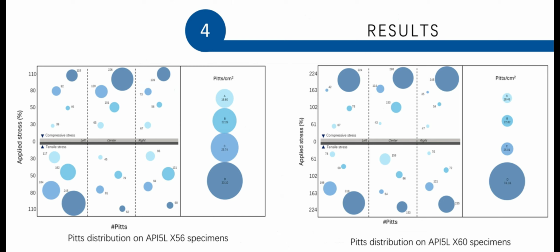Now, what were the results we obtained? Since pits are nucleation sites for cracks, a count was performed on each specimen. It was observed that in both steels, the number of pits increased with the applied load. The higher the load, the greater the number of pits. Additionally, the load condition, whether in tension or compression, was evaluated, and it was found that the load points in the 3-point bending test act as concentrators where the higher number of pit colonies were located.